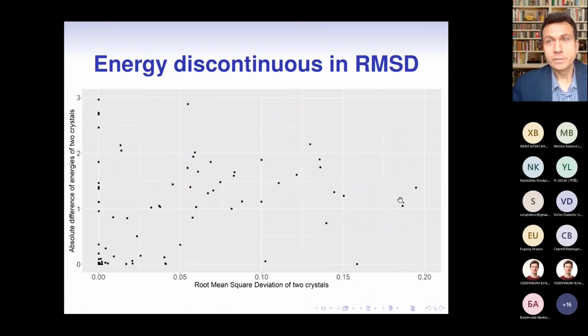What are other methods? So let me first show the experimental comparison calculation of RMSD. So in this plot, every small square represents a pairwise comparison. On the horizontal axis, you see the RMSD value, so comparison for 2 crystals taken from that large T2 dataset mentioned previously. And on the vertical axis, it's the absolute value of the difference of energies between the same 2 crystals. And it is easy to see that on the vertical axis, we have many pairs of crystals when RMSD is exactly 0, so really 0, but energy values are different. So it means that energy is simply discontinuous on RMSD. If you perturb only slightly, the energy can change largely.